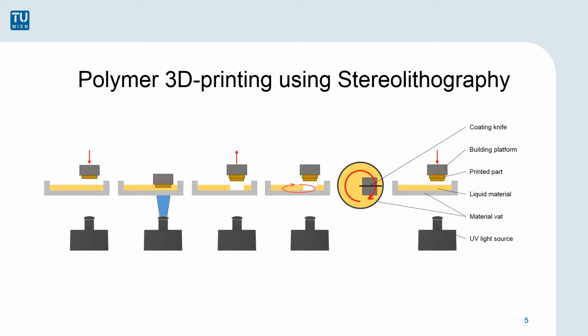The liquid material inside the vat is exposed to a UV light source, which induces the solidification of the resin. The hardened material sticks to the building platform. After the solidification of the first material layer, the platform is moved upwards and the vat is coated with fresh liquid resin by a coating mechanism. Repeating this process, we can build a three-dimensional part layer by layer. In this particular study, the samples are a composite consisting of inorganic tricalcium phosphate and organic polymers. These samples tend to be very stiff and show almost no elongation at break, resulting in a very brittle behavior.